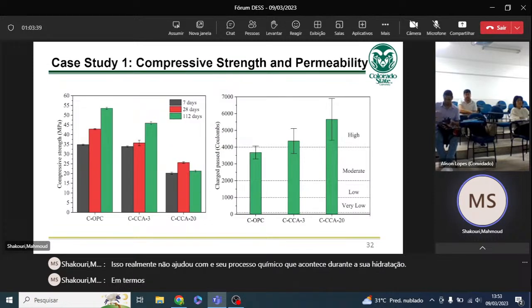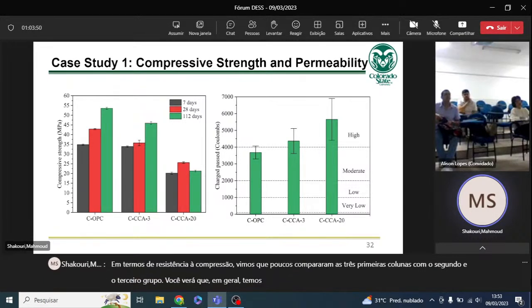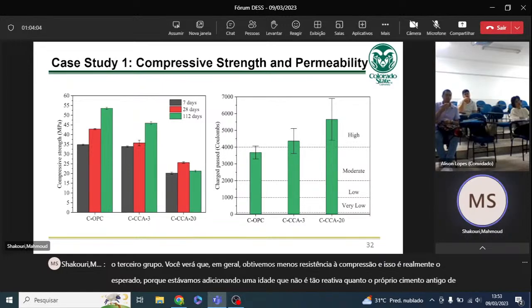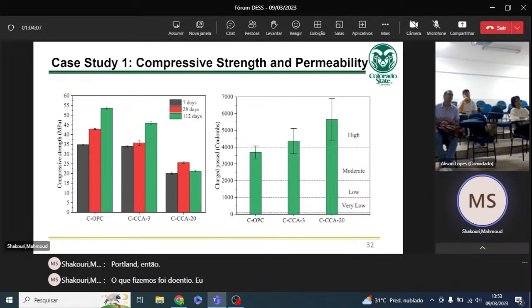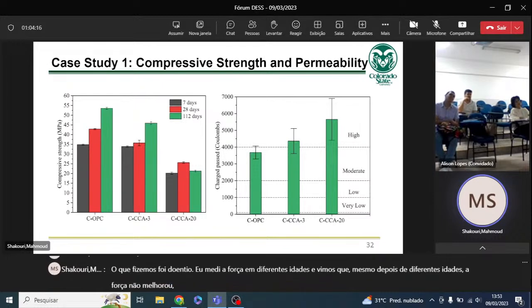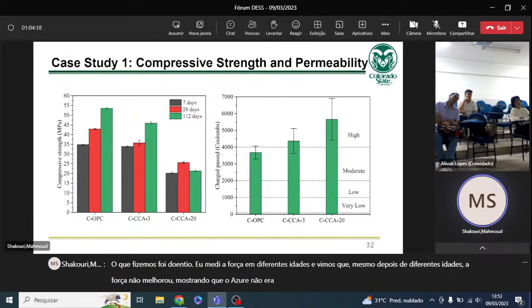In terms of compressive strength, if you compare the first three columns with the second and third group, you'll see that in general we got less compressive strength, and that was expected because we were adding an ash that is not as reactive as the Portland cement itself. So we measured the strength at different ages, and even after different ages, the strength did not improve, showing that the ash was not really reactive.